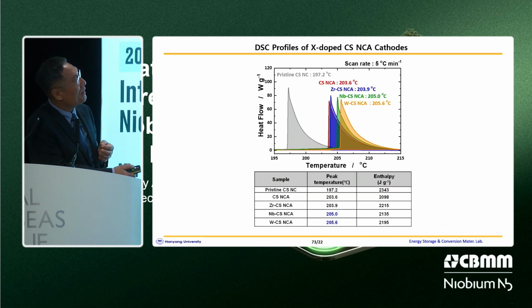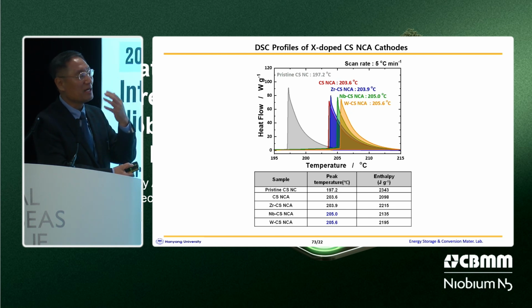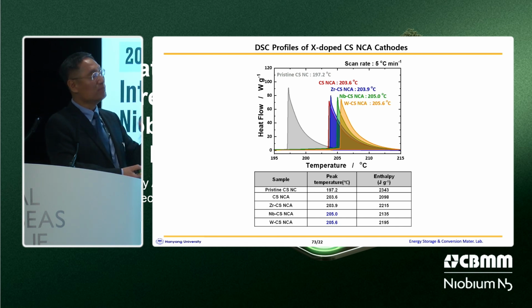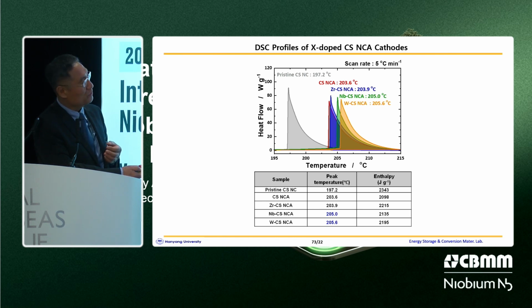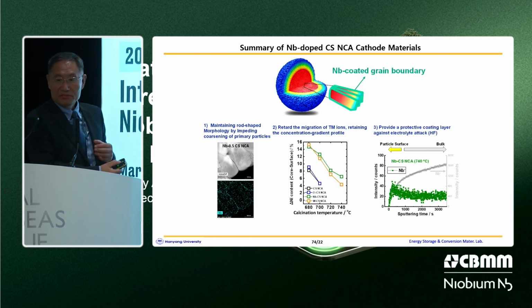And this is the thermal stability of the prepared cathodes. As you can see, the niobium and tungsten-doped cathodes slightly improved thermal stability compared to other cathodes. However, I believe that after long-term cycling, the niobium or tungsten-doped cathode will show further improvement in thermal stability too. And this is a summary of niobium-doped NCA cathode materials.